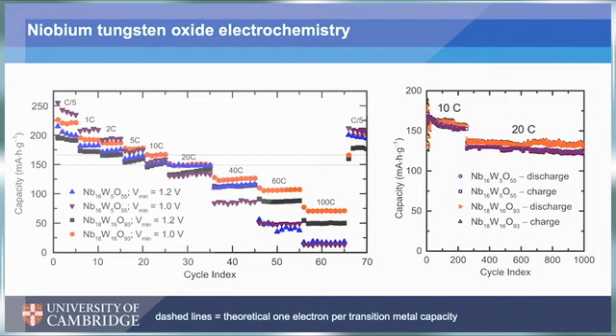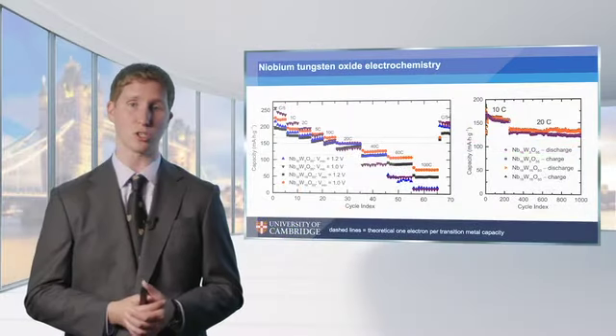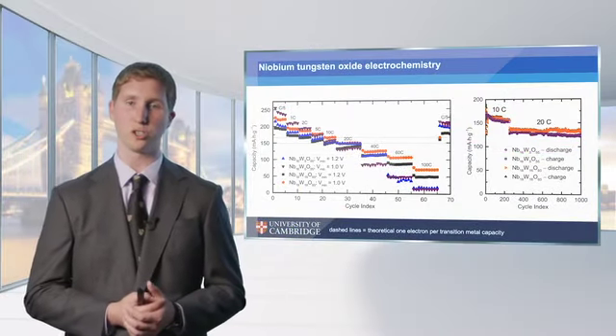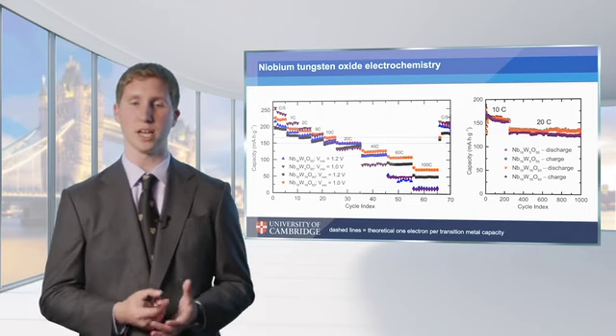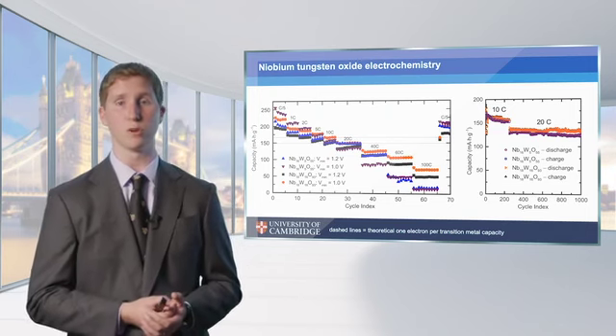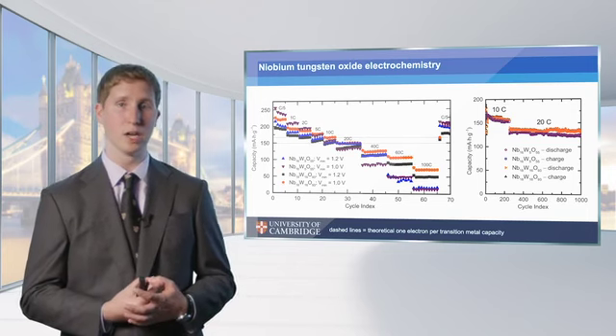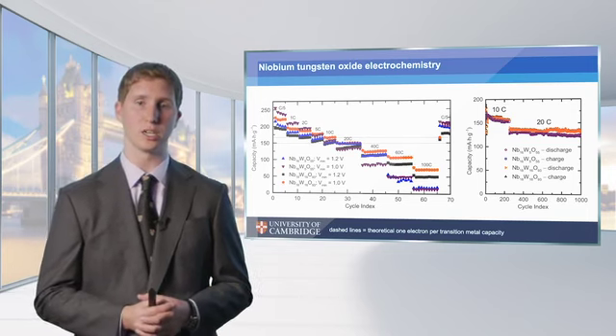And so we wanted to test what the durability of these were as well. So we did 1,000 cycles, 250 at 10C and 750 at 20C, and observed only about a 5% loss in capacity over 1,000 cycles, indicating a projected cycle life of many thousand cycles for these materials, but inherently indicating that these bulk micron structures are stable to full charge-discharge lithiation at very high rates. And so that's an inherent advantage they have over graphite as well, in addition to being safer, doing these high current density charge and discharge.